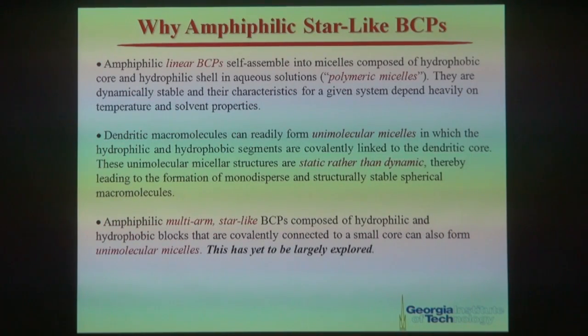Now the question that follows is, why do you want to study amphiphilic star-like block copolymers? Before we get to that, we know amphiphilic linear block copolymers can self-assemble into polymeric micelles, right? These polymeric micelles are dynamically stable, and their structure for a given system depends heavily on temperature and solvent properties, among many other parameters. On the other hand, we know dendrimer, this particular dendritic polymer, can readily form unimolecular micelles, in which the hydrophilic and hydrophobic segments are covalently connected to the dendritic core. These unimolecular micellar-like structures are static rather than dynamic, thereby leading to the formation of monodisperse and structurally stable spherical macromolecules. In theory, amphiphilic multi-arm star-like block copolymers can also form these unimolecular micelles. This, however, has yet to be largely explored.